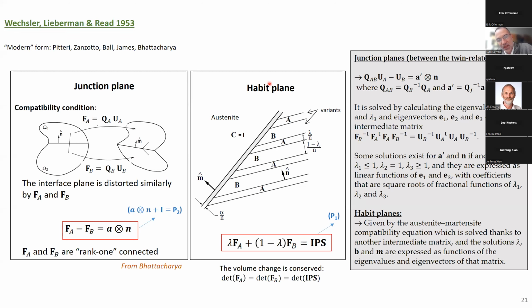And they also use another equation to establish a compatibility between the average distortion matrix made by the two variants, A and B, and the austenite. So here it's the average of the two distortions, just a linear average of distortions, and at the end you should get an invariant plane strain equal to the P1 of the first version. Okay, these are the two main equations of the second version of PTMC. Behind that, you still have a lot of equations to solve to get your solutions. It's not so direct, actually.